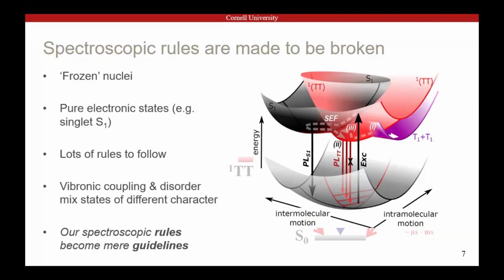And taking this concept, we can see, for instance, that states that should be totally dark, non-interacting with light, can actually very readily emit photons. States that should be static on the timescales that are relevant for organic solar cells can actually move remarkably long distances. So when we understand when the rules can be broken and find ways to control this, we can actually start to apply these materials in entirely new ways. That's kind of the principle behind most of the research we do.